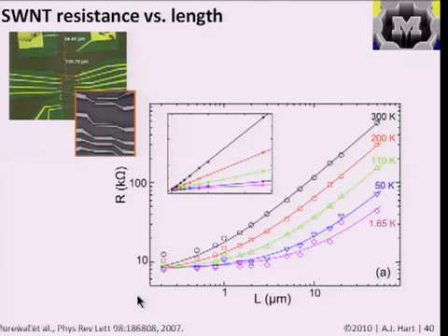And so this more complete picture lets us understand or visualize the picture that we saw last time, where these researchers fabricated devices with very long single-wall nanotubes strung between different electrodes. These electrodes are just like pairs of fingers that let them measure the resistance across the same single nanotube at different separations. You measure the voltage-current characteristics, and therefore calculate the resistance across a small gap by connecting your multimeter here to here, or you can measure it over a larger gap by connecting it along this long distance.